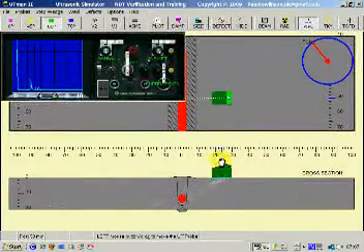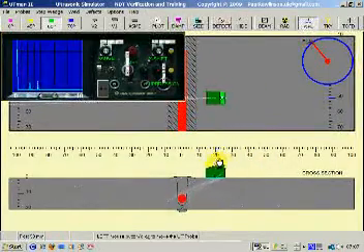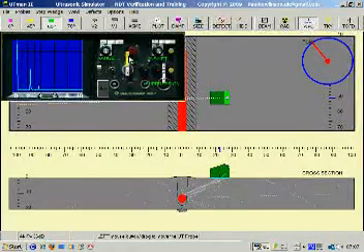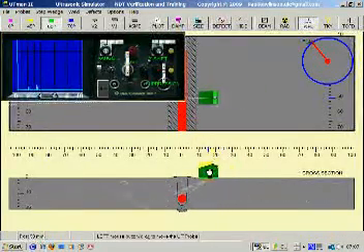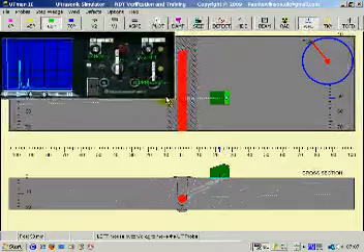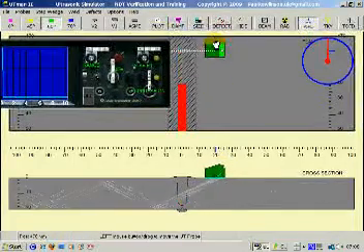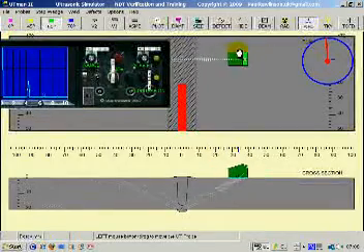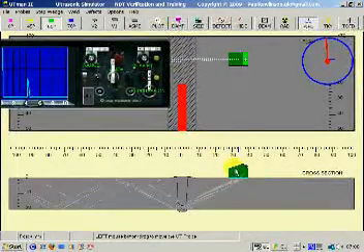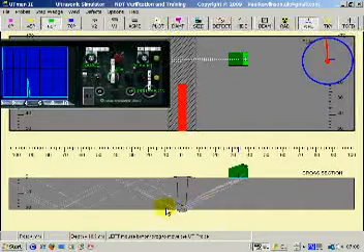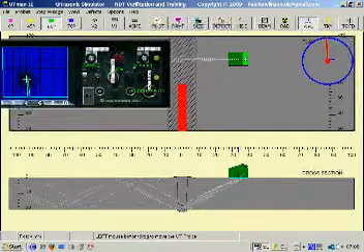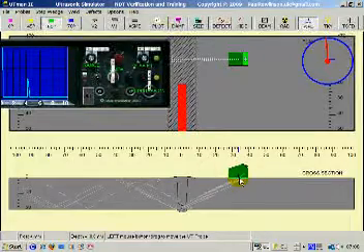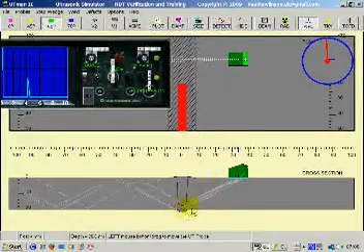And here we can now detect this defect. I'll increase the amplitude. Now if I was looking at a part of the weld where there was no defect, we can see the root. The sound is travelling through the metal and hitting the root, hence this echo here at 40mm distance from the probe to the root.